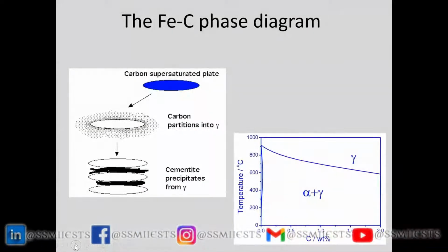So this is the mechanism of the bainite transformation on the left. The plate forms like martensite, it then partitions carbon, and then you get cementite precipitation. You can suppress the cementite precipitation by adding silicon or aluminum. And the phase diagram on the right shows that the solubility of carbon in ferrite that is in equilibrium with austenite is incredibly small. You know, the maximum is about 0.028%. So this is just a part of the equilibrium iron carbon phase diagram. Next slide.